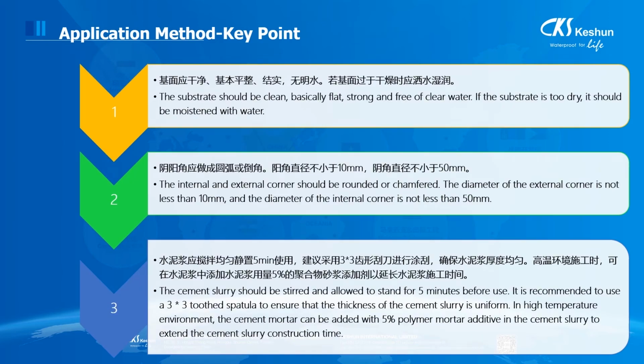I think we all know how to use bitumen primer to apply membrane, but most of you don't know how to use cement slurry as primer. You can see number 1, the substrate should be clean, basically flat, strong, and free of clear water. If the substrate is too dry, it should be moistened by water. When you use the cement slurry as the primer, if the substrate is too dry, the substrate will absorb all the water immediately, and then there's no water for the cement to react. So you need to remember this one.